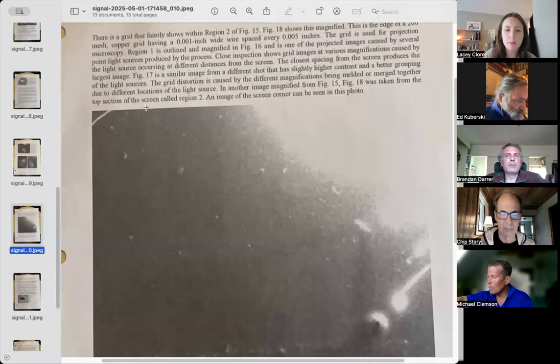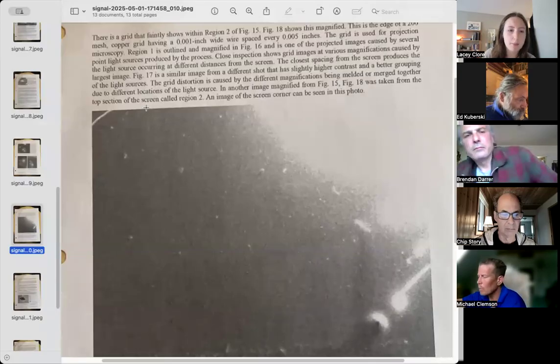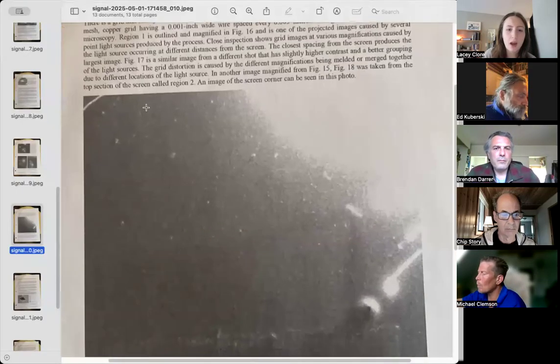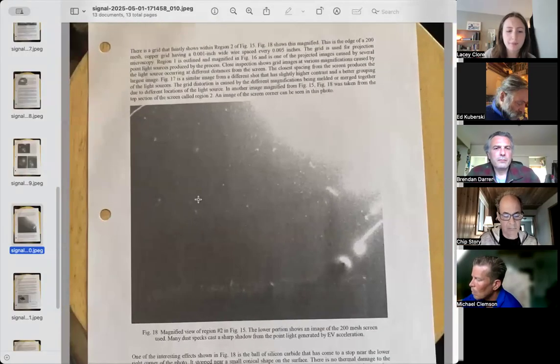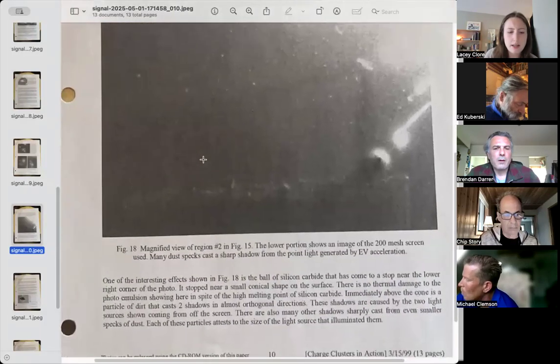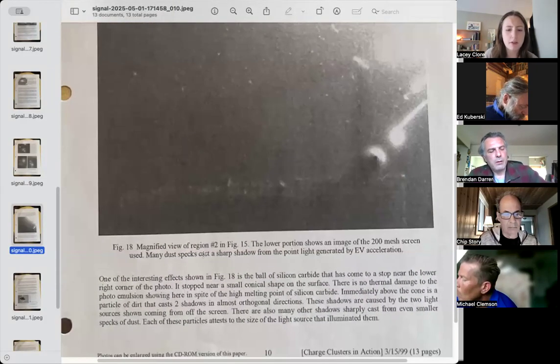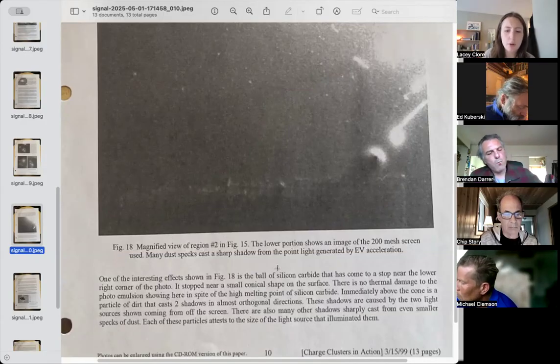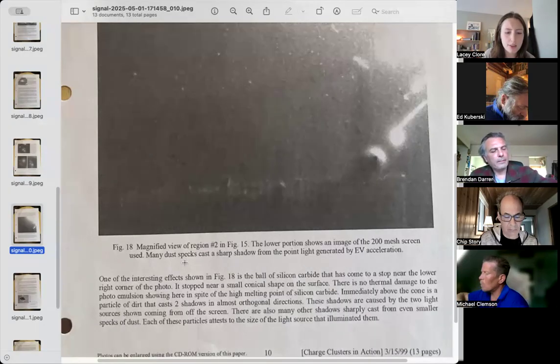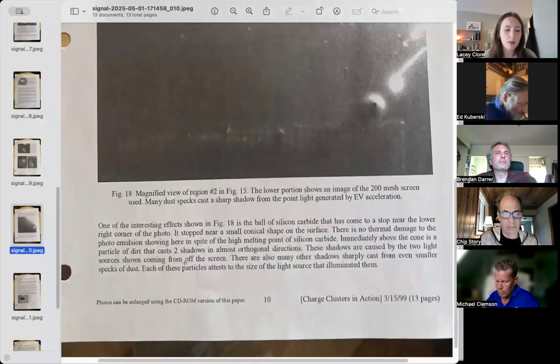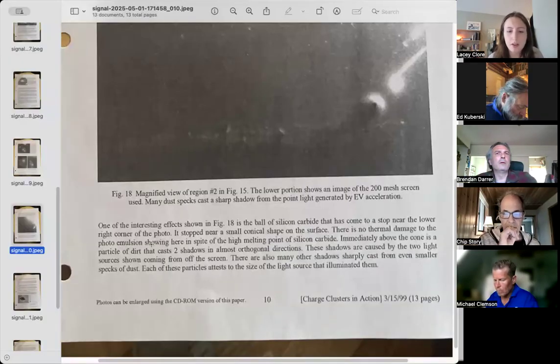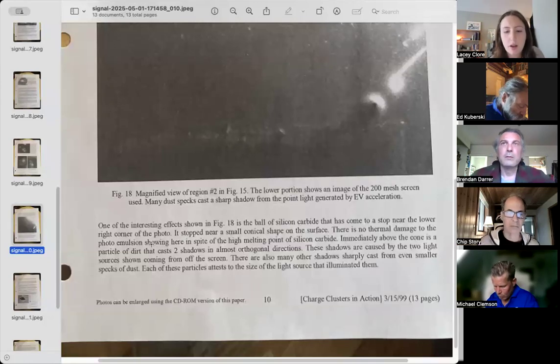And another image magnified from figure 15, figure 18 was taken from the top section of the screen called region 2. An image of the screen corner can be seen in this photo. Figure 18, magnified view of region number 2 in figure 15. The lower portion shows an image of the 200 mesh screen used. Many dust specks cast a sharp shadow from the point light generated by EV acceleration. One of the interesting effects shown in figure 18 is the ball of silicon carbide that has come to a stop near the lower right corner of the photo. It stopped near a small conical shape on the surface.